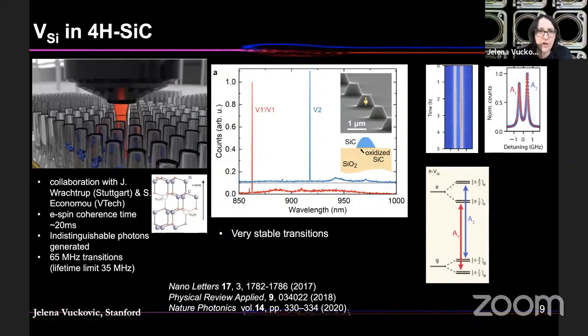This is something that I mentioned at the very beginning. There are several types of silicon carbide that have different lattices. We focus on 4H, and in this particular polytype, there is also a number of different color centers that various groups are working with. We are primarily focusing on the silicon vacancy in silicon carbide. This is essentially just a missing silicon atom inside of a lattice of silicon carbide. And since there are different symmetries of the spots where you can have a missing silicon atom, you have different transitions that we refer to as V1 or V2.